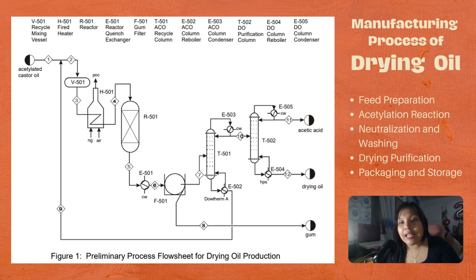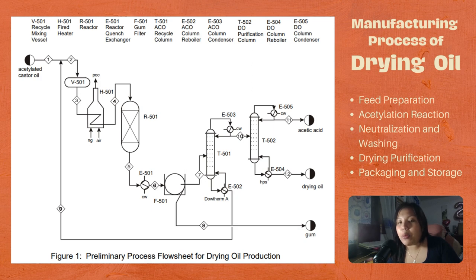As the liquid proceeds to T-502 (another distillation column), acetic acid is formed, of which 99.5 percent goes to an exiting stream, and drying oil is extracted as a 99.5 percent byproduct. This distillation column operates at atmospheric pressure. The drying oil is further dried and purified to ensure the final product meets desired quality and specifications, removing any remaining water or impurities. Like any other product, drying oil undergoes quality control to ensure the efficiency of the product before packaging and distribution.